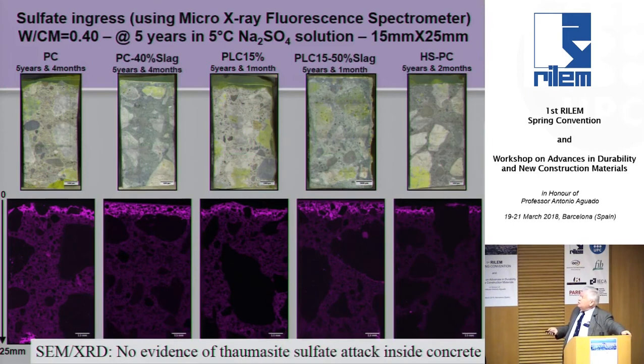And we did some microstructural work. I'm not going to show all that because of time. We've done X-ray diffraction, SEM work, and we found no evidence of Thaumasite sulfate attack inside the concrete. These are just some thin sections that we then did X-ray microfluorescence on just to look at the sulfate penetration from the surface, and then we also put these into the electron microscope later on.